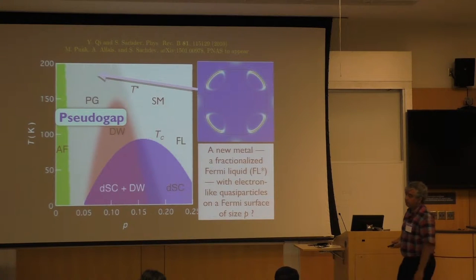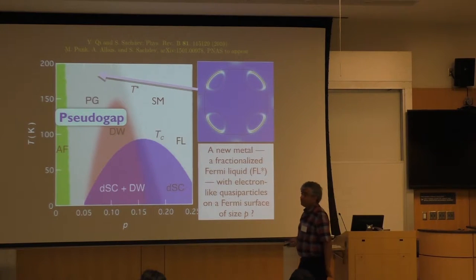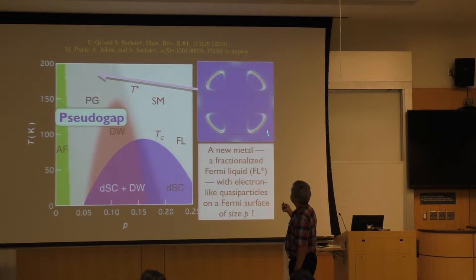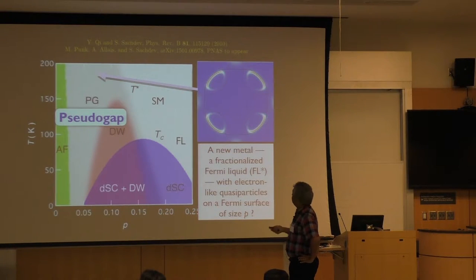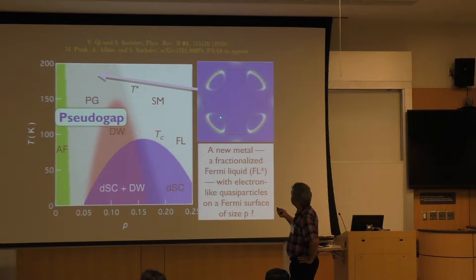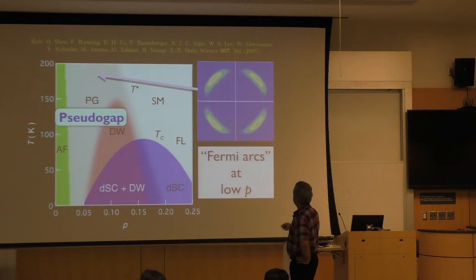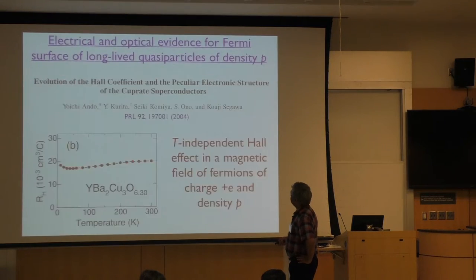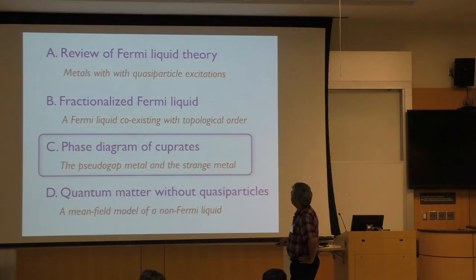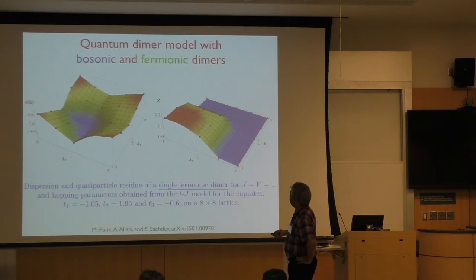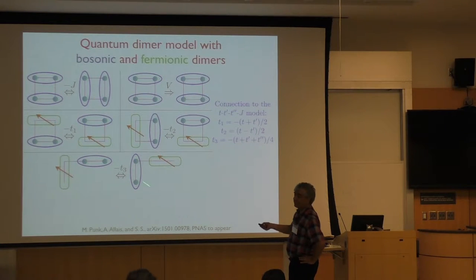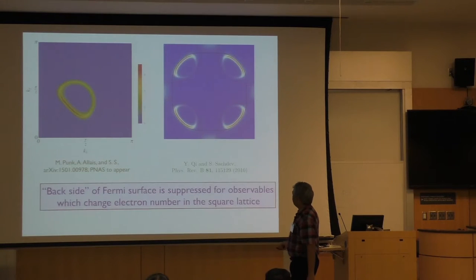This is our momentum space — Kx and Ky. Those dashed lines are the pockets I drew earlier. You take these green dimers — that's the crude picture — they form little Fermi pockets. This calculation showed this is the kind of thing they form. What I didn't talk about was the residue — there's a quasiparticle residue which has to do with the wave function of the quasiparticle. And that turns out to have a highly anisotropic form.